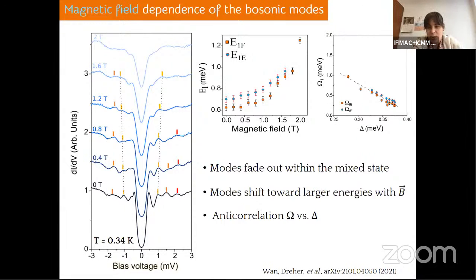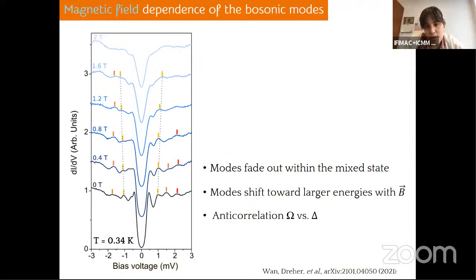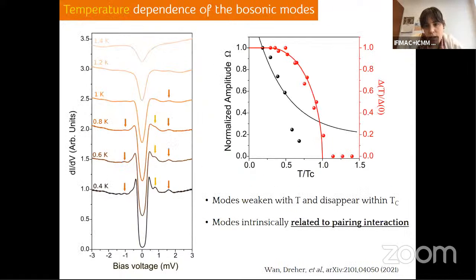Thank you. Nice talk, Miguel. I have a question because you have shown this anti-correlation between the gap size and the energy of the bosonic mode when you increase the magnetic field, and also when you look at the changes of the superconducting gap as a function of the position. But when you look at the temperature dependence, you see a positive correlation. There, the size of the superconducting gap decreases, and the amplitude of this